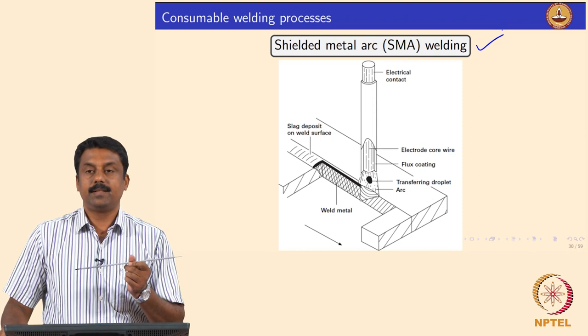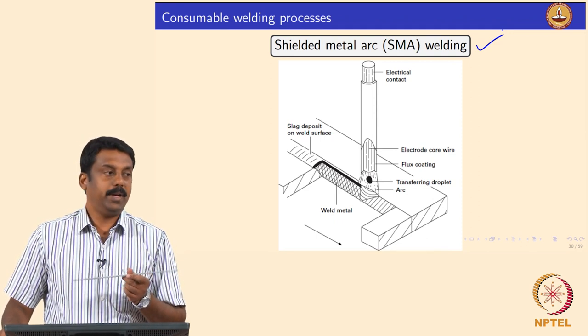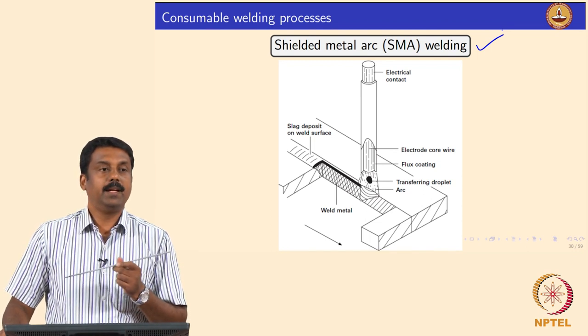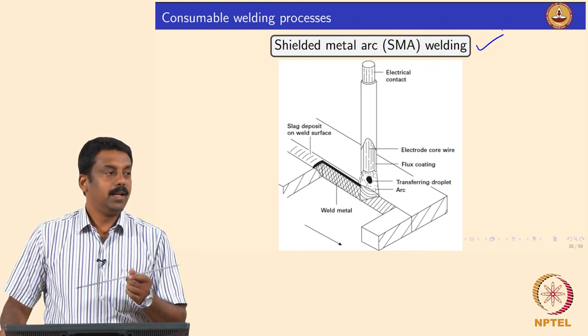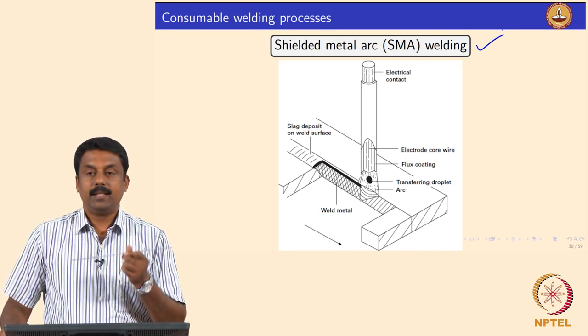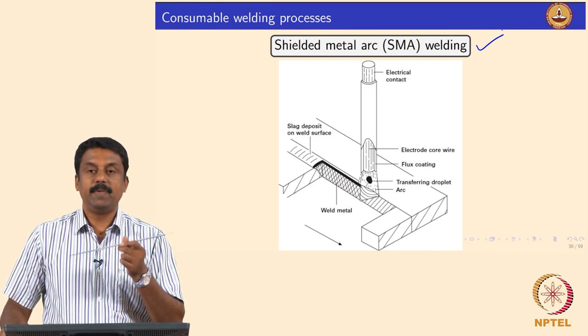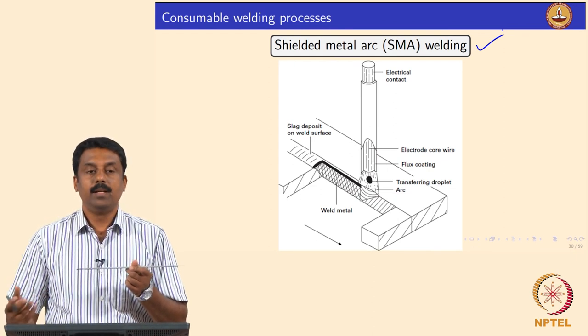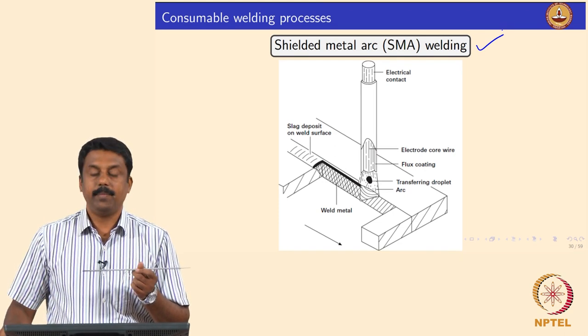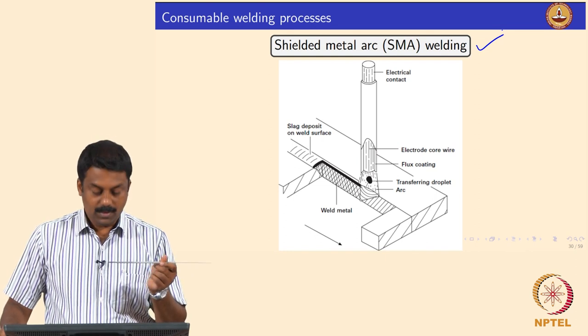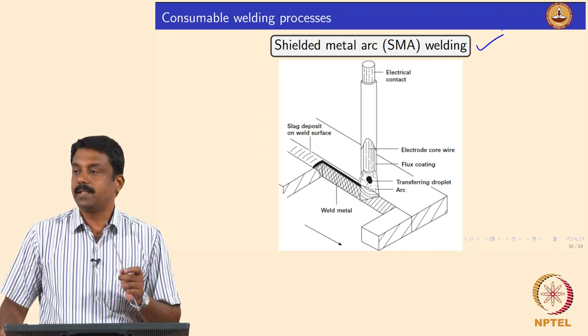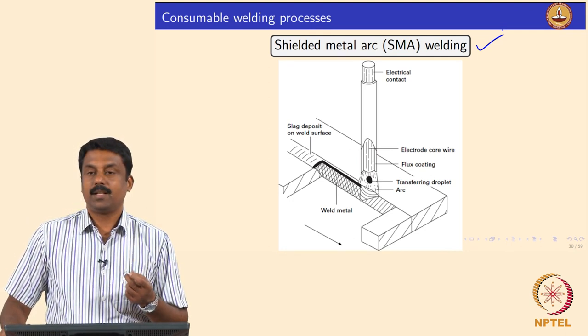In most cases the flux contains calcium carbonate to generate carbon dioxide, and then we add other fluxes like titanium oxide or calcium fluoride to change the surface tension and thermophysical properties of the liquid metal, so that droplet transfer can be promoted in either globular or spray mode. The system is very simple — you just need a power source which can give a low voltage current.